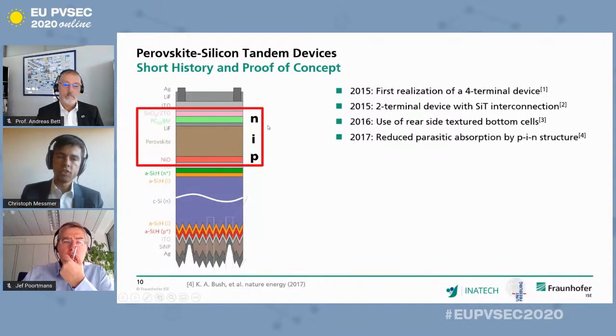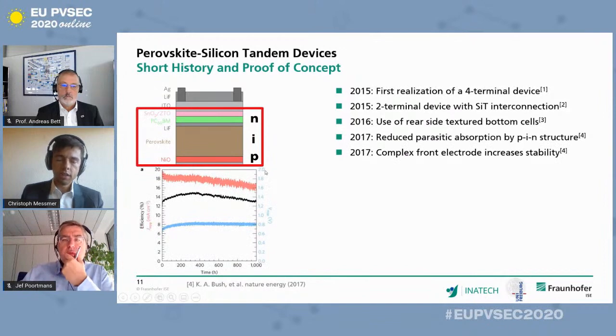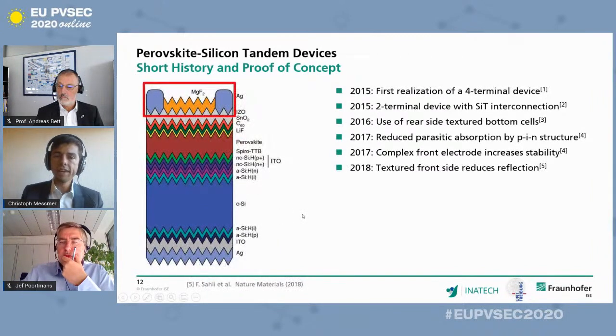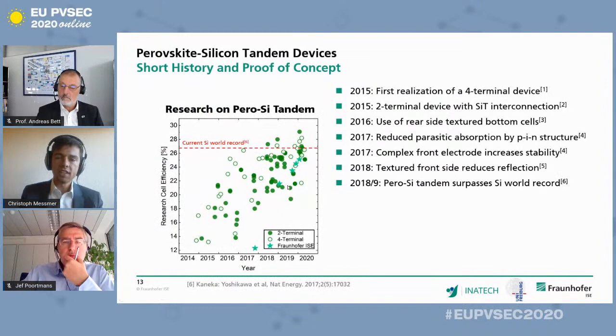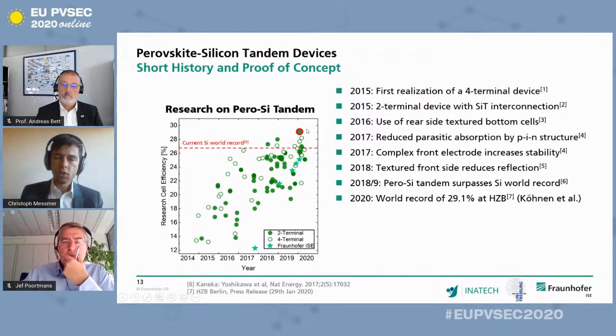2016, the use of a rear side textured bottom cell increased the light trapping properties. 2017, the switch to the PIN structure reduced parasitic absorption. And also in the same year, in the same publication, we've seen that the complex front electrode increased the long-term stability of the devices. 2018, a proof for textured front side was shown, which significantly reduces reflection losses. And from 2018-19 on, the perovskite silicon tandem surpassed the silicon world record shown here in red, mainly due to the better passivation quality of the perovskite absorbers. And currently, we're at a world record of 29.1% at Helmholtz Zentrum in Berlin, where I want to refer to Eike Köhnen's talk this afternoon. And also I want to refer to Patricia Schulze, who will talk this afternoon about the results at Fraunhofer-ISE shown here by the green stars.